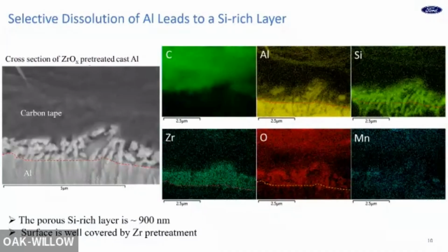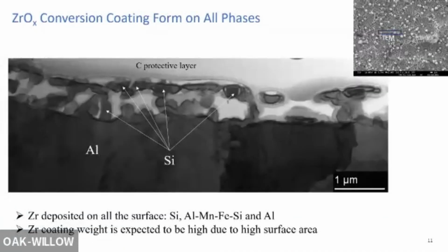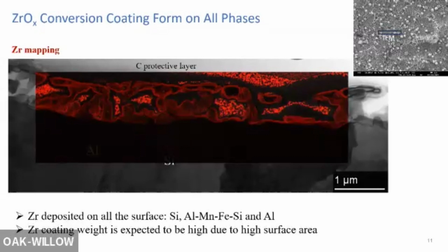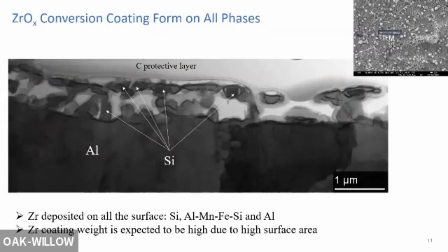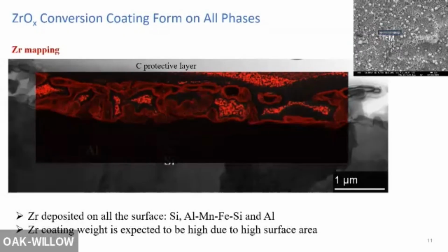So to have a better understanding about this zirconium formation on this porous structure, we did a TEM analysis. We take a small sample here, and this is the cross-section. You do see this porous structure. This is the silicon, and there's some porosity under the silicon. If you look at the zirconium distribution on the surface, back and forth, you can see it's covered almost all the free surface. You do see here the bright dots is an artifact during the EDS analysis, so nothing over there. So it seems that the zirconium covers the whole surface, but this alloy, the porous structure, has a very high surface area due to the porous structure, so you can imagine the coating weight can be very high.